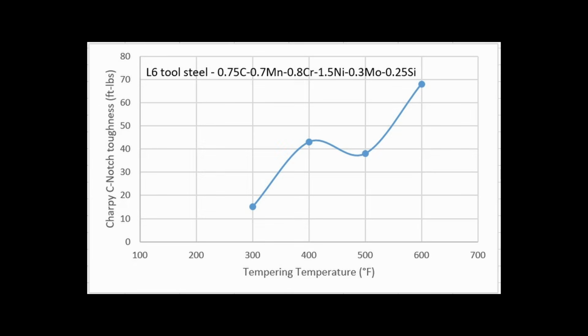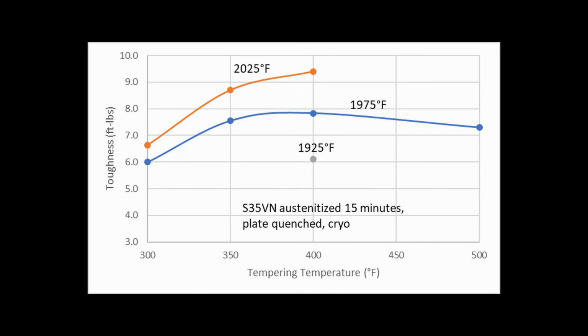On the subject of tempering, there is a phenomenon called tempered martensite embrittlement, where when you temper within a certain range, the toughness is reduced even though the hardness also went down. This typically happens in the range of 500 to 700 degrees Fahrenheit, though the exact temperature where it starts varies by steel. With S35VN, I found that tempering at 500 degrees led to a reduction in toughness versus a 400 degree temper. The toughness didn't fall off a cliff, the steel isn't ruined, but if you have reduced both the hardness and the toughness, then we have made the steel worse. We could have both higher hardness and toughness, which is what we want.